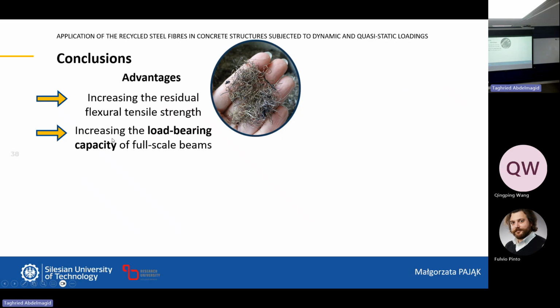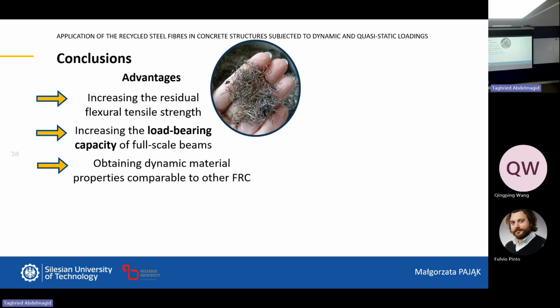this conclusion is also very important because we were testing other beams with other kinds of fibers, and the scatters between the results were much bigger. So we got the beams where there was completely no influence, and we got the results when there was a huge influence. So this is connected with the orientation of the fibers. And in case of these fibers, because there are a big number of the fibers everywhere inside of the beam, we didn't get so much scatters. So this is very important. A conclusion.